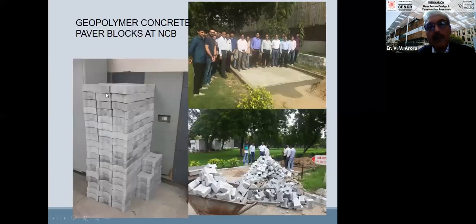This is geopolymer concrete paver blocks. We made this in our laboratory at NCB when I was in NCB. This is a photograph of a pavement we made there as a test stretch. We made it here, and this has performed well. This is the M35 grade of blocks we had created. There were minor issues, but because of the equipment and all that; once we use better equipment, those issues will not be there. And this is a very good material.